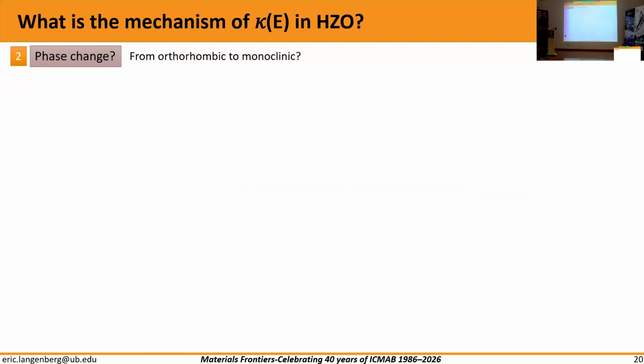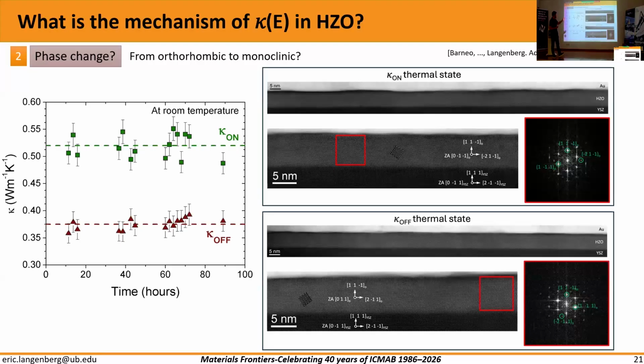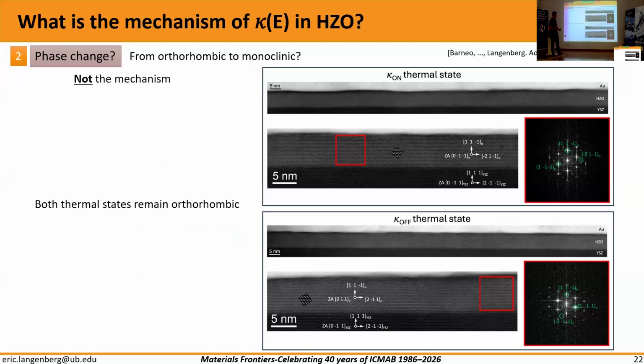Our second guess was, are we inducing a change of phase with an electric field? It could be, because this material is orthorhombic, but it's actually metastable. The stable phase is monoclinic. Might we be inducing a phase transition with an electric field? Could be. But the thing is, in both the on state and the off state, the film remains orthorhombic. So we are not inducing any phase transition in our films. So what remains? Well, this is not the mechanism.